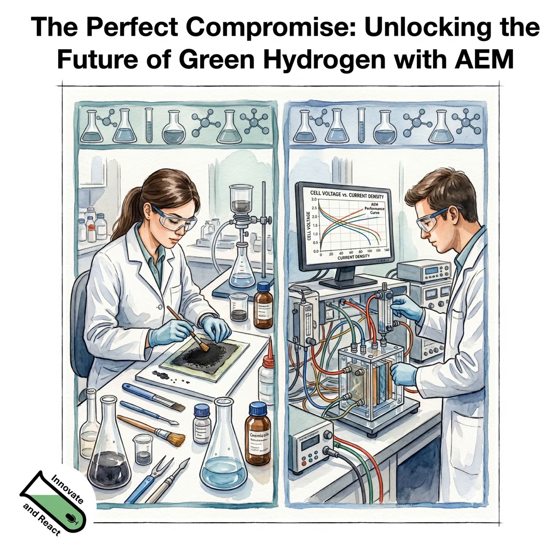If you look at us, for example, on the one hand, it's always interesting and important for us, as we're looking at real-world systems, to distinguish the losses and to really link the losses with ex situ data. So that's what Miriam mentioned, like measuring sulfur content in your electrolyte afterwards, or doing REM EDX measurements, like how your materials change. And we are capable of doing that, so it's always good to have everything regarding that in-house to see how stuff changes after a certain amount of time or certain amount of stresses, but also to employ some tricks. So that's one of my favorite topics, to distinguish the losses is to reintroduce a reference point into our cell system.